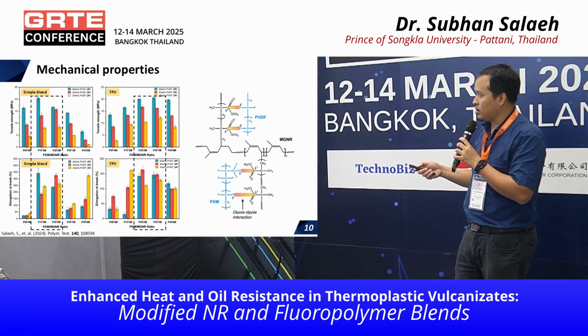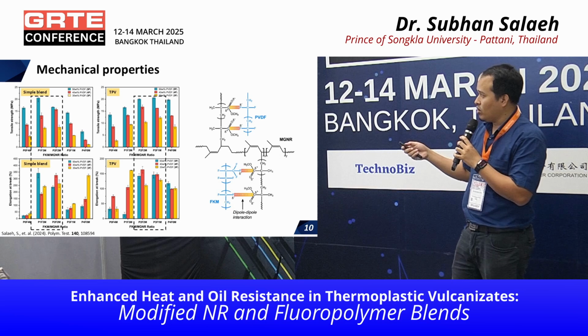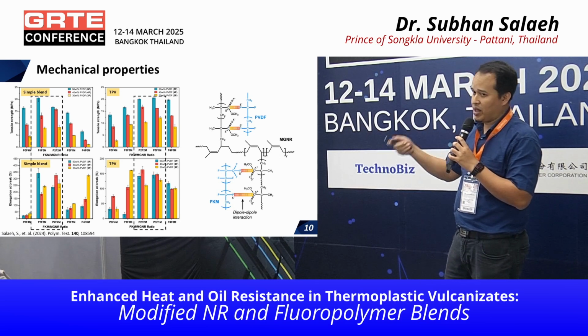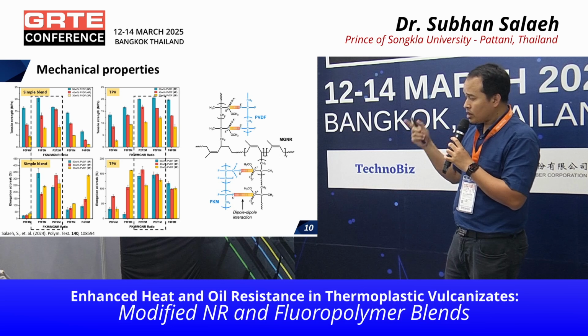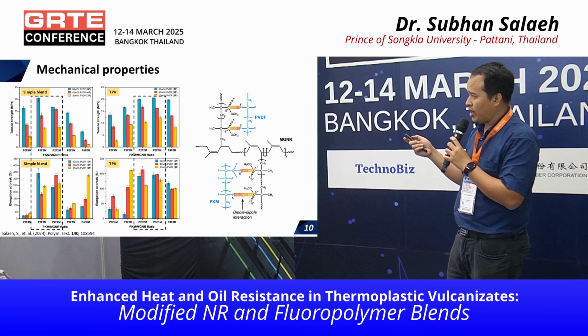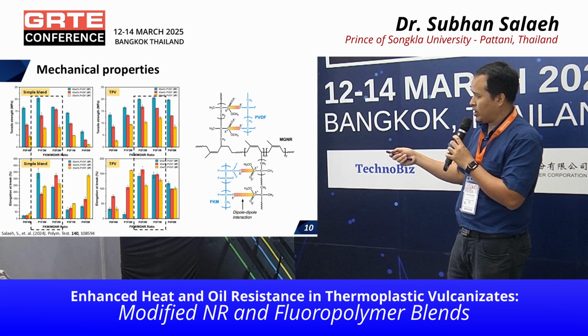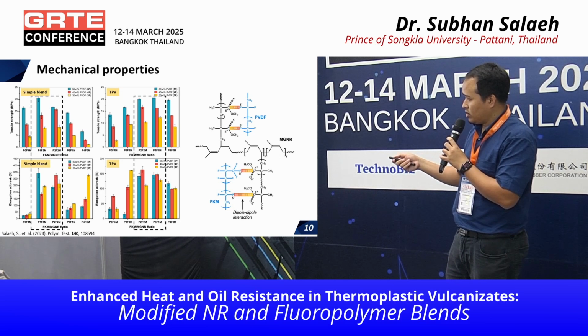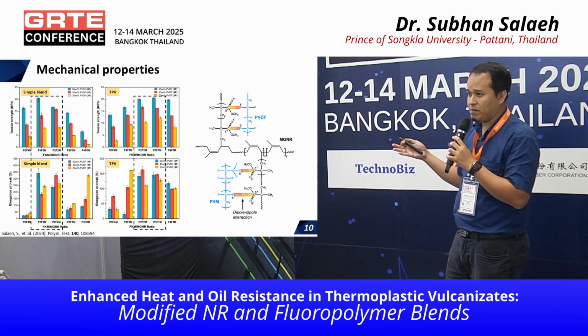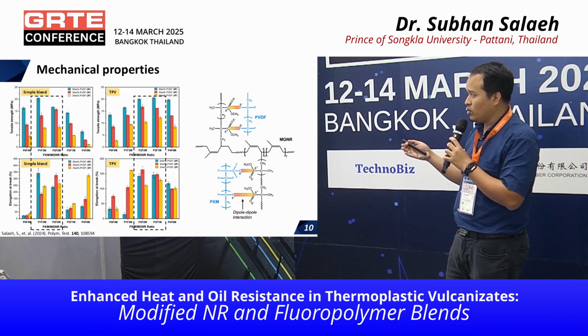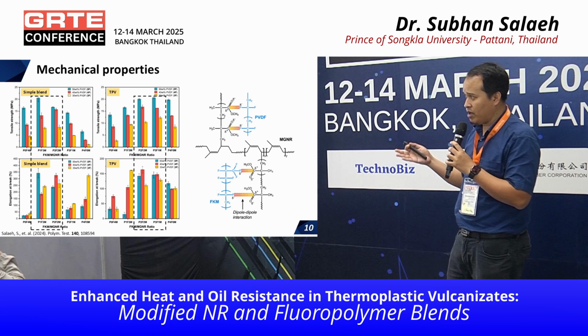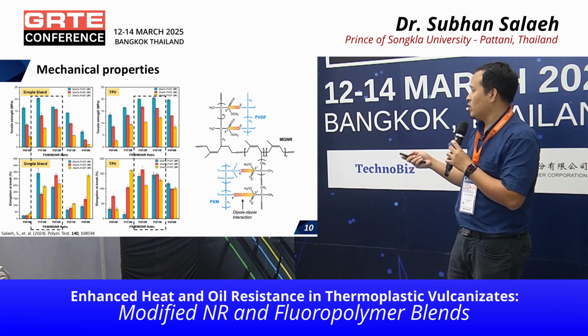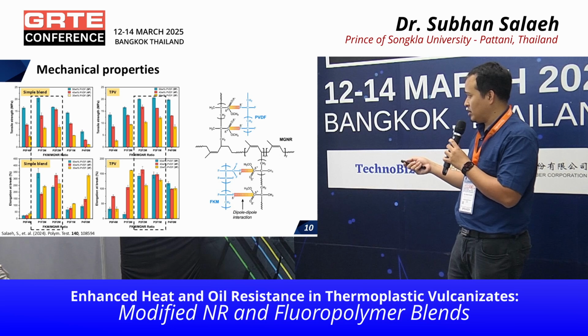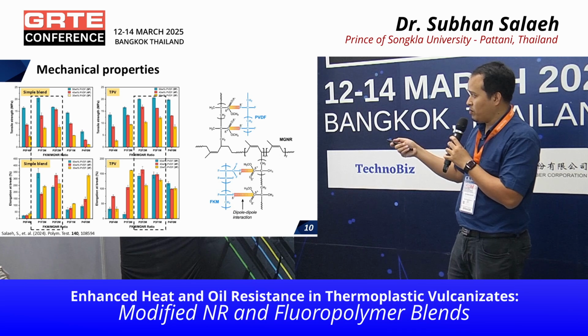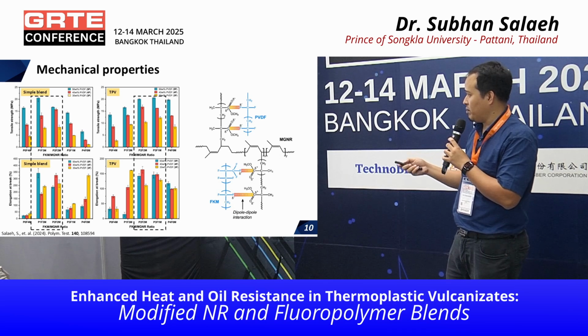So this is the result, and when we increase... On the left hand side is the binary blend with only PVDF and MGNR, and on the right hand side is only PVDF and FKM, and we can show that the ternary blend shows better properties than the binary blend. It is due to the good interaction between FKM, MGNR, and PVDF. The good interaction comes from dipole-dipole interaction between acrylic rubber, PVDF, and FKM. So that's why we improve the properties of the ternary blend.